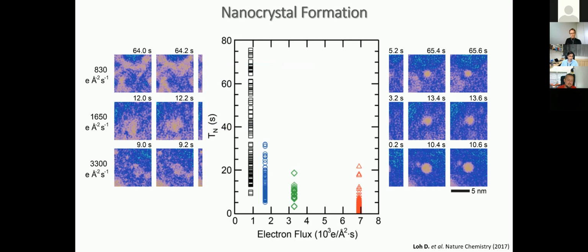It's not always a friend, but in this particular case, it happens to be working with us. And just to show that this is a purely beam-driven phenomenon, this is a distribution of the nucleation times as a function of the electron flux for these samples, right? So more beam, faster nucleation or faster crystallization. While we can somehow justify saying the beam does this and that, this is not entirely a system that is free of beam artifact. When you synthesize a crystal on a benchtop, you do not bring a microscope next to it and shine a beam to make it, right? So you can use all the justification in the world, but at some point we have to try to do experiments that are relevant to common synthesis or growth or nucleation phenomena.